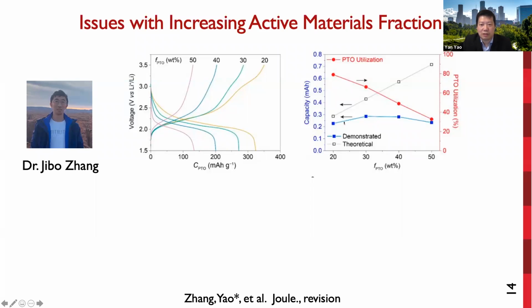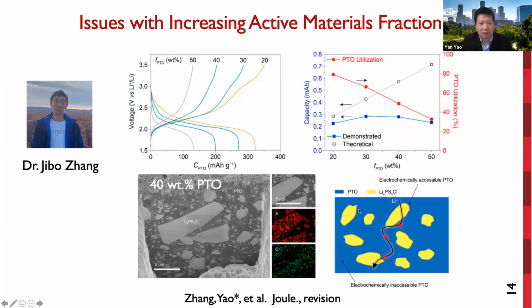So in other words, the capacity didn't scale with PTO ratio following this theoretical line, but reached a plateau and did not further increase. Jibo found the origin of this low utilization is due to the unfavorable microstructure. Electrolyte islands with size between 2 to 15 micrometer were surrounded by a sea of PTO and carbon mixture. Such a microstructure is unfavorable for lithium ion transport because the electrolyte couldn't find the percolation network, and the PTO has a lower ionic conductivity for lithium-ion transport.